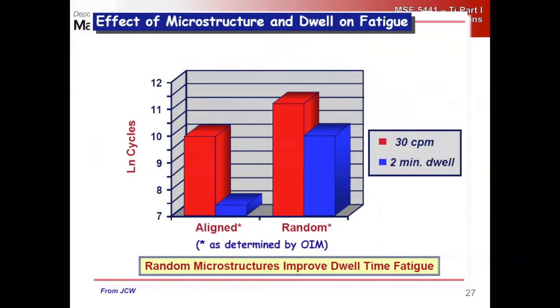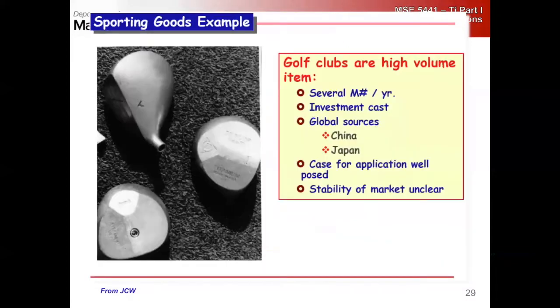And this dwell fatigue issue is still kind of an ongoing thing, because every so often a part will fail and they'll look at it and it'll have these huge macro zones and no one quite knows why, because it's such a rare event phenomenon now that the new forging processes are in place, right? So in some ways the problem is solved because 99.9% of the parts are fine, but then there's still that 0.1% oddball that pops up. And we really don't know why or where it's coming from.